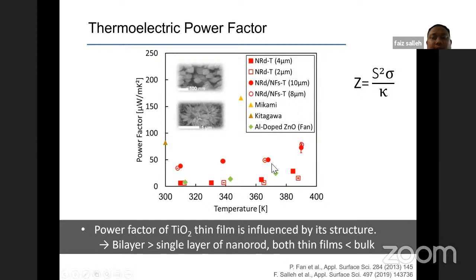If we relate this to the thickness, we also know that the thickness does not influence the phonon drag contribution if we have this kind of thickness, around a micrometer. That's why we can see here that the thickness does not have much influence on the thermoelectric power factor of this nanostructured TiO2 thin film.